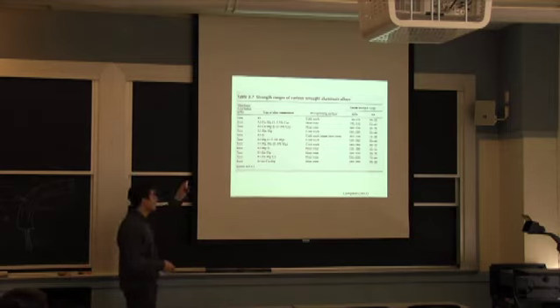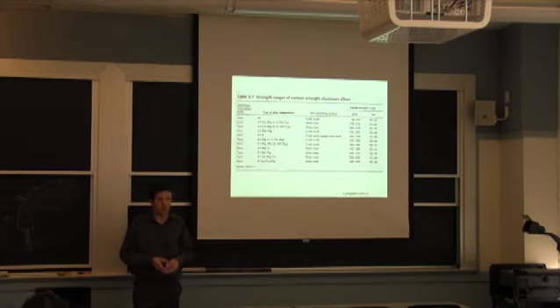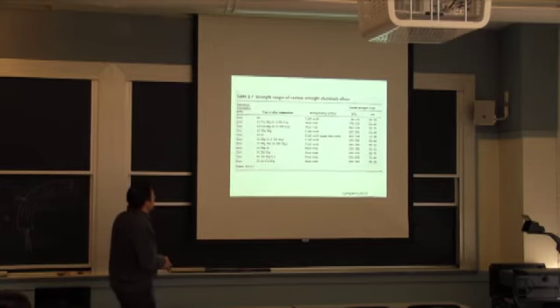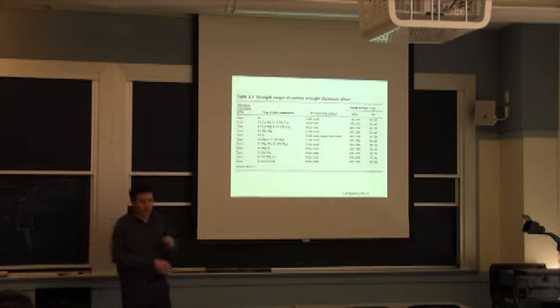If you look at the other alloys here, you can also have significant corrosion, pitting, deterioration of the finish, and you can have stress corrosion cracking, even if your pH is seawater or a normal, nearly neutral pH. If you have chlorides and other impurities, that's what drives the deterioration of the aluminum. We do alloy the aluminum, therefore, for strength. It's not for corrosion resistance, it's not for conductivity, it's for strength and toughness.